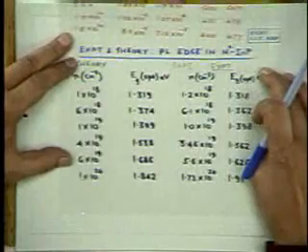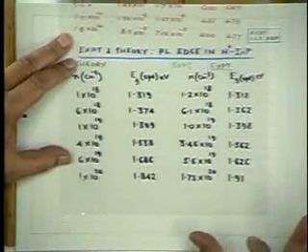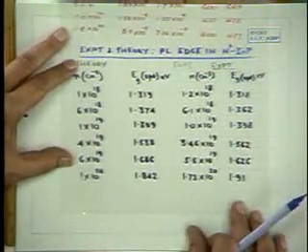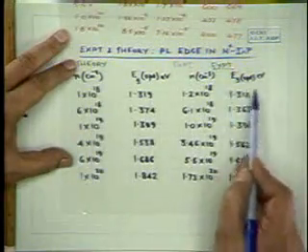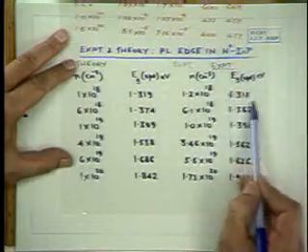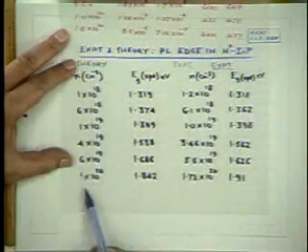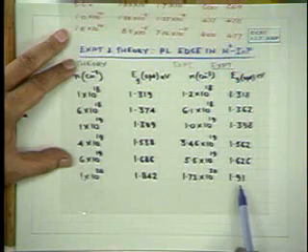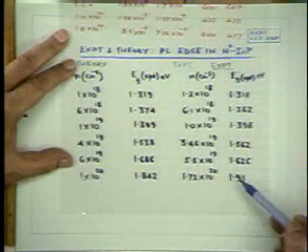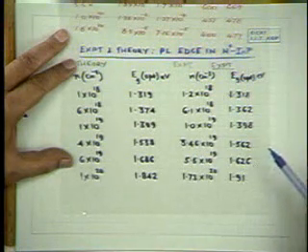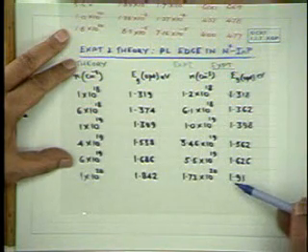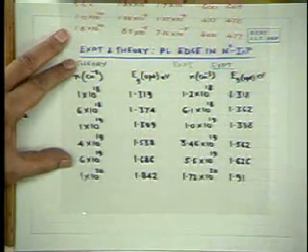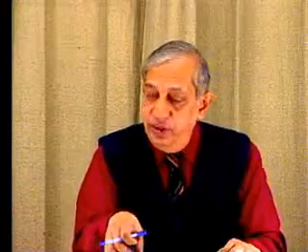and if you just see these results, this table sums up all the results obtained in our laboratory, that if you have a doping of about 10 to the power 18, then the edge is near 1.31 as expected. And if the doping goes up to 10 to the power 20, the edge shifts to 1.91. So there's a considerable shift in the photoluminescence edge or the optical edge, and it is not just the Moss-Burstein shift. The Moss-Burstein shift, if you did not take the band gap shrinkage into account, this value calculated would be something like 2.1 or 2.2. So there's an increase due to the Moss-Burstein shift, and there's a decrease due to band gap shrinkage. So these points are very important when it comes to studying the optical properties of lasers and similar materials.